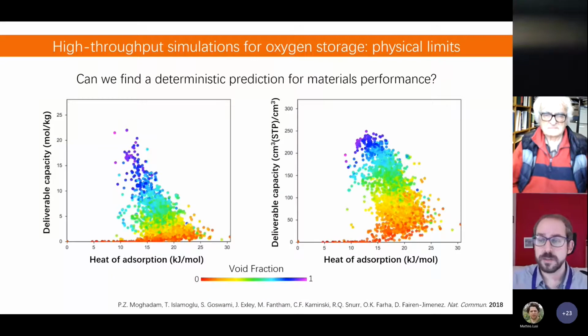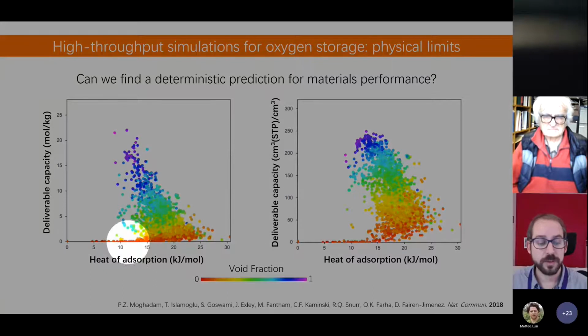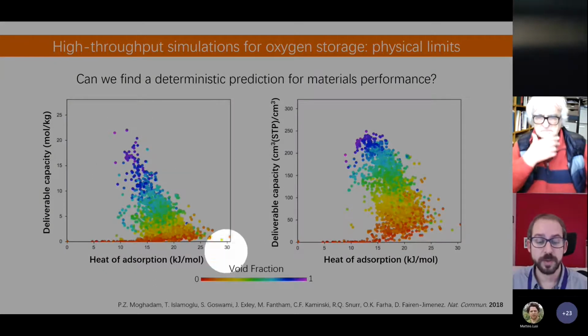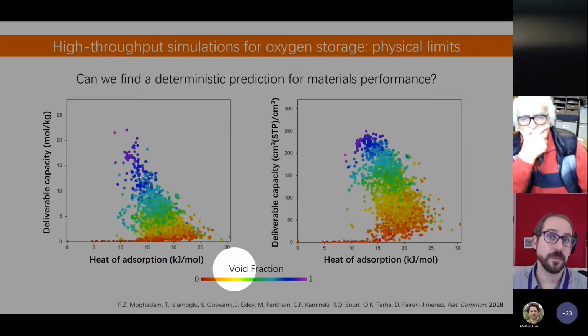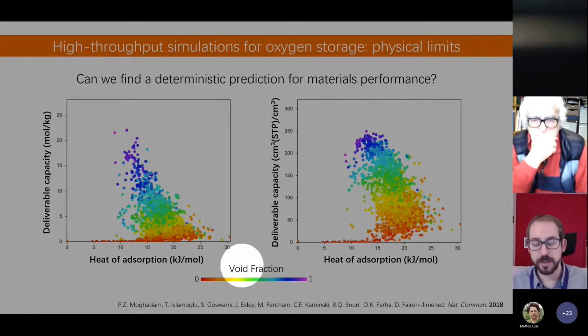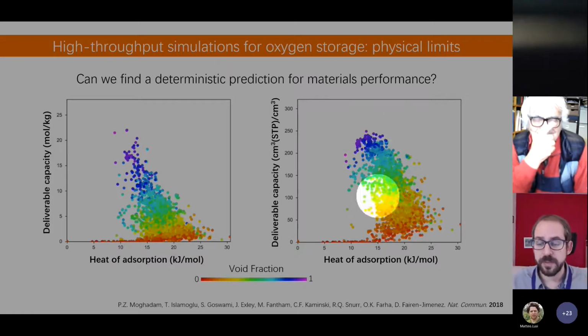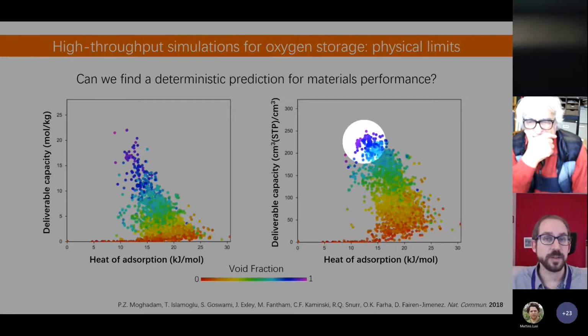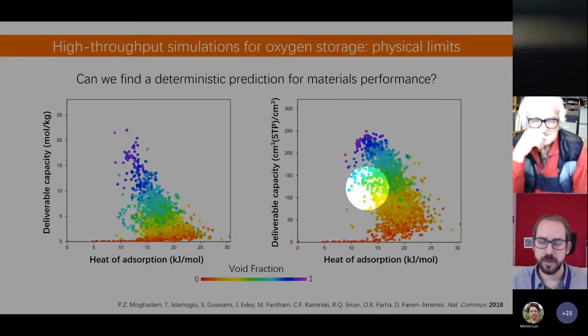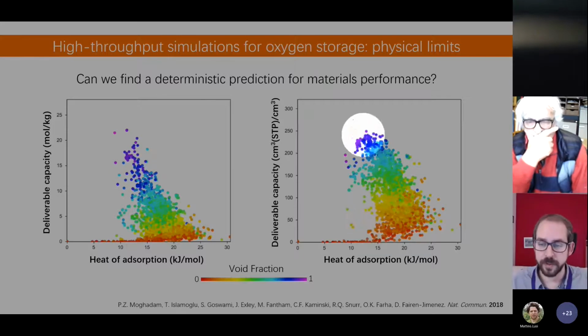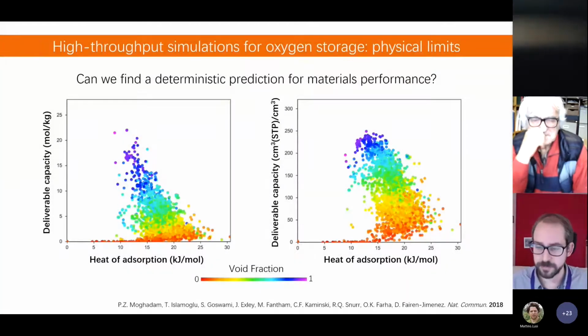The key question is that this is, again, a multidimensional problem. I need to pay attention not only to the interaction, but also to the porosity of the materials. In this case, this is the void fraction, how porous the material is. And we can find optimal values for interaction, but optimal values as well for the void fraction. In this material it was about 0.9, if I remember correctly, for all this representation that I have here.